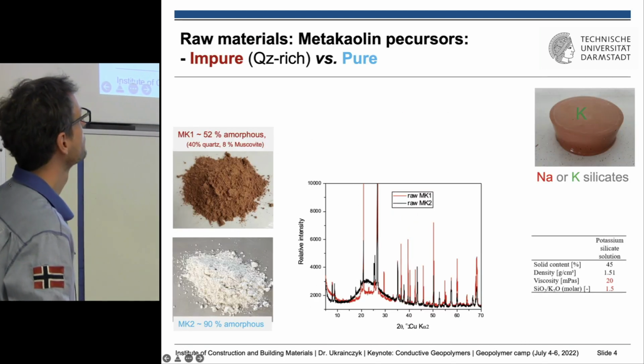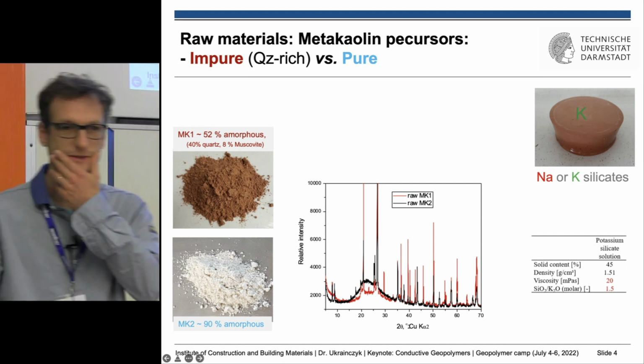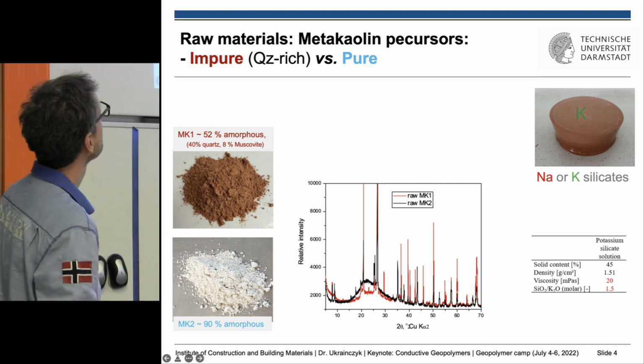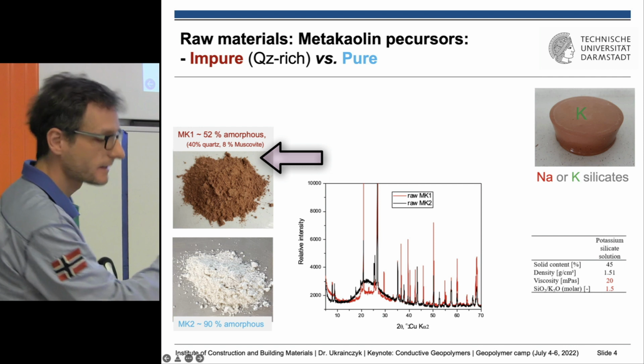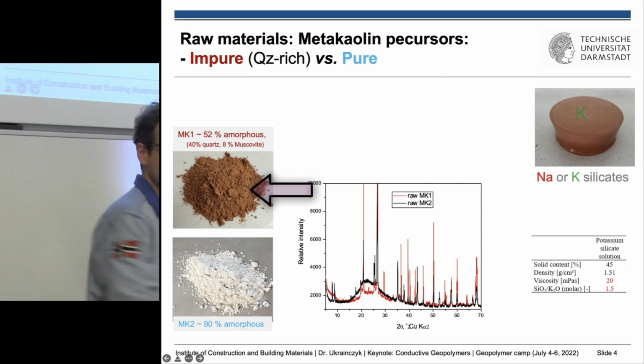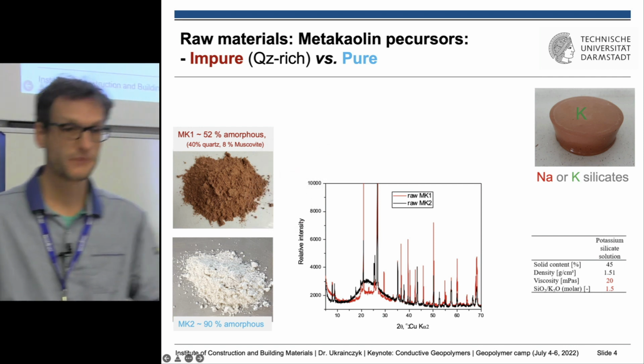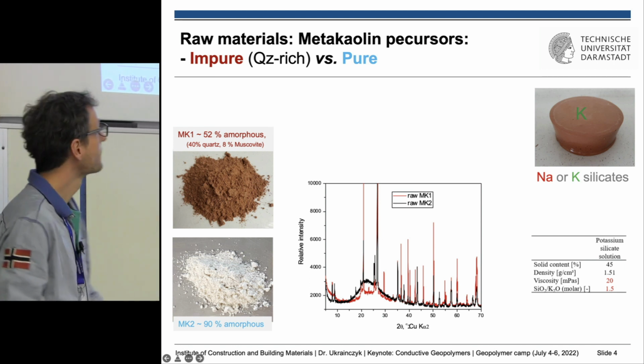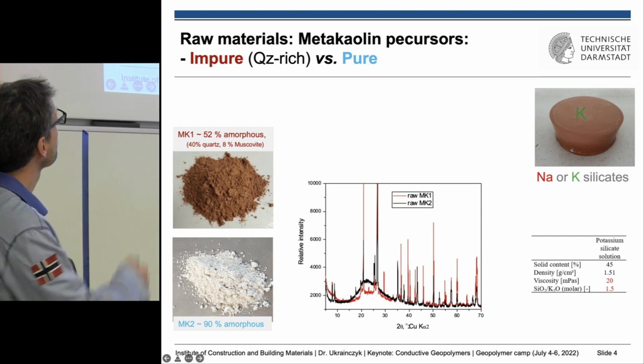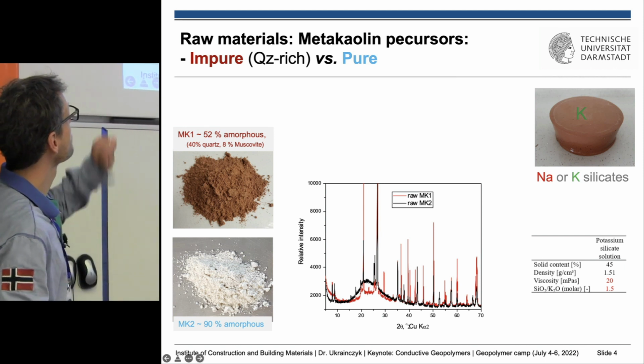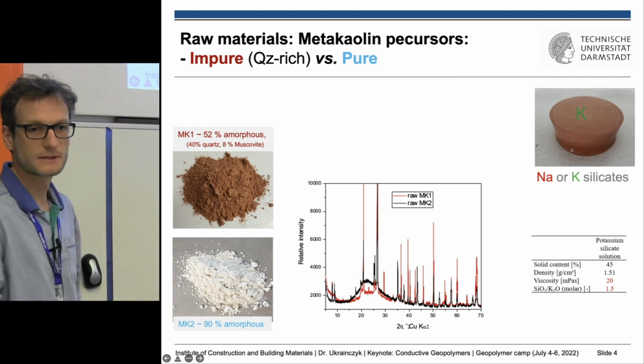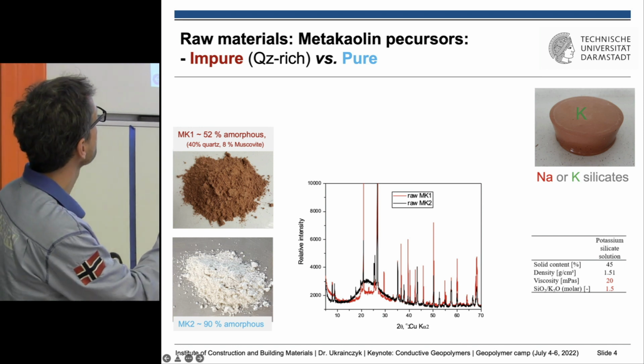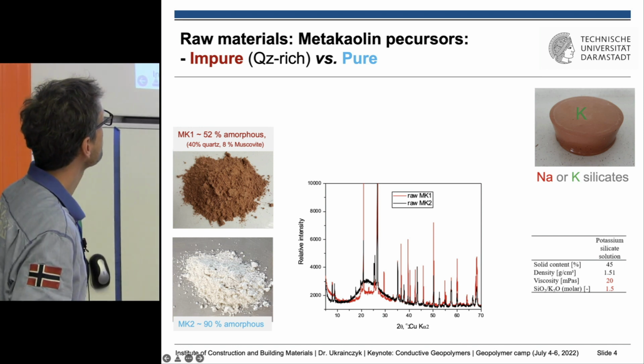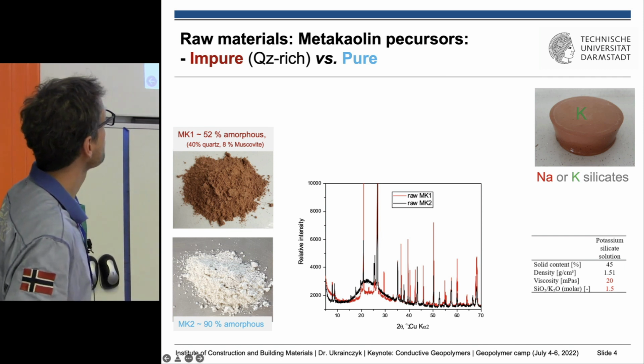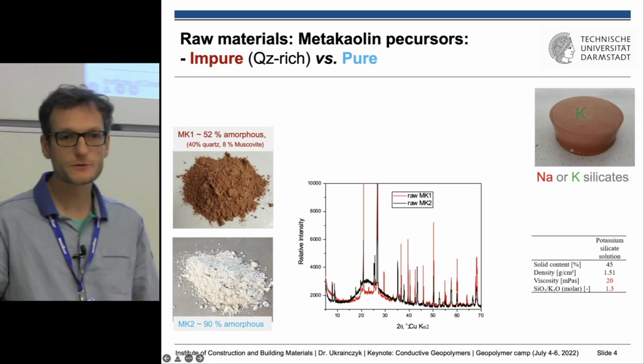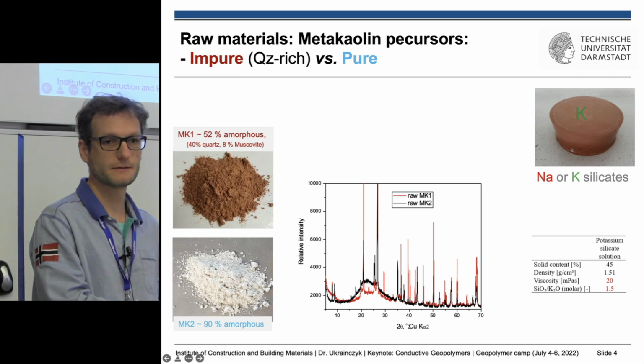So the raw materials, we already heard a lot about the raw materials. For the clay, metakaolin, we are using this red clay, I could say. You can see it here. It's one of the ferro-polysialates, and very interesting. It's also not so pure. We did the XRD quantitative analysis with Topas, and we found quite a lot of quartz. But roughly it has 52% of amorphous content, which we could say is the metakaolin in it.